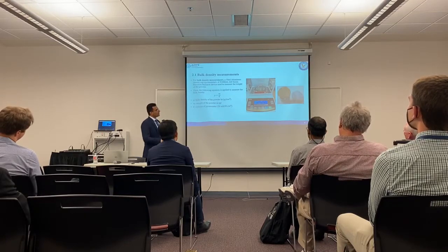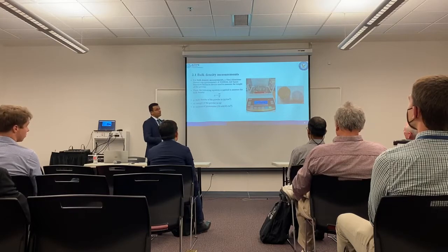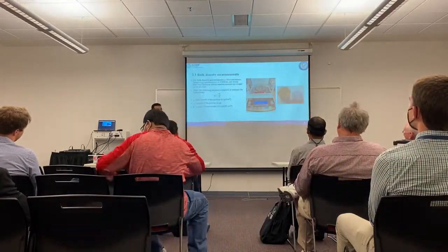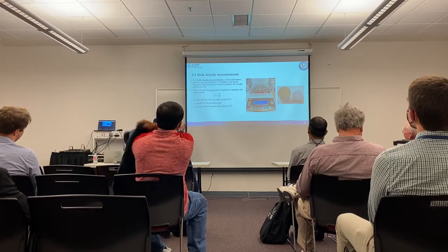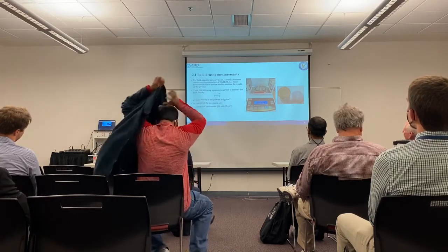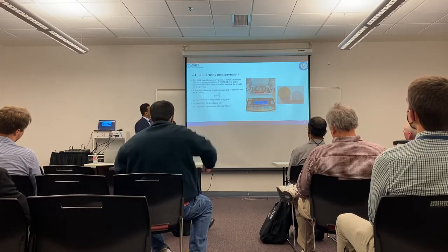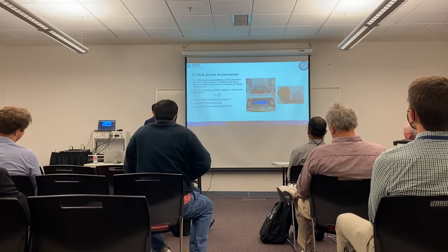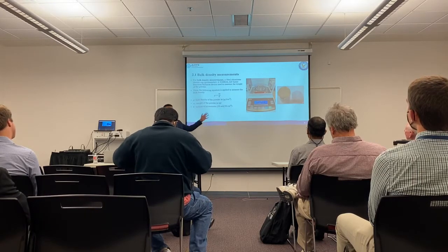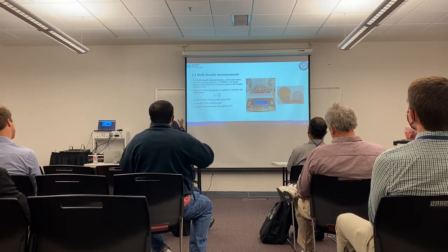For example, we used a pycnometer. This is our density cup, a 50 milliliter pycnometer. We put this powder, for example, this is oak leaf powder. We put it in and tap it 5 times to make sure there are no cavities. After that, we have to reach a closed system. Then we apply it here in the scale device to measure the exact mass for each powder, I mean. After that, we apply this normal equation, mass divided by volume, to get bulk density. We ran this 5 times for each powder to make sure about the average.